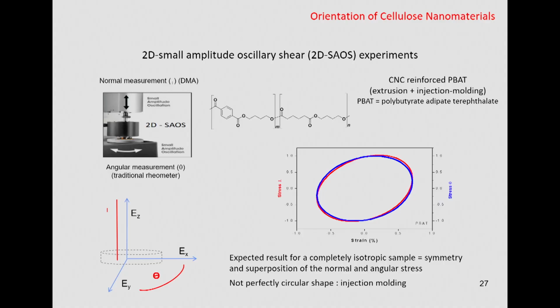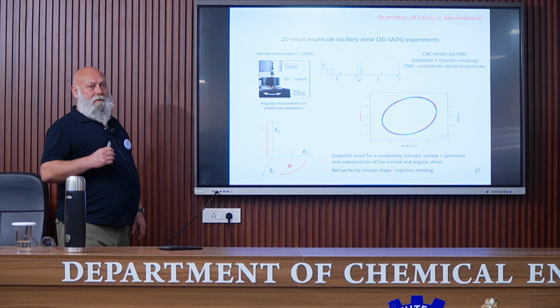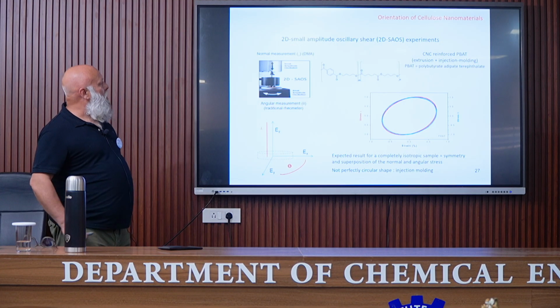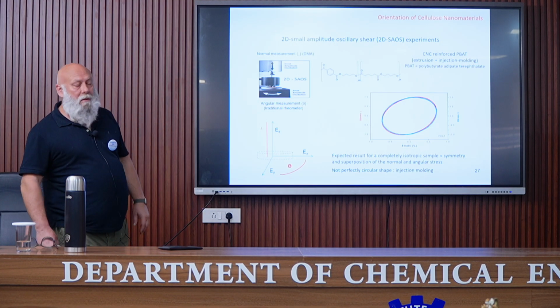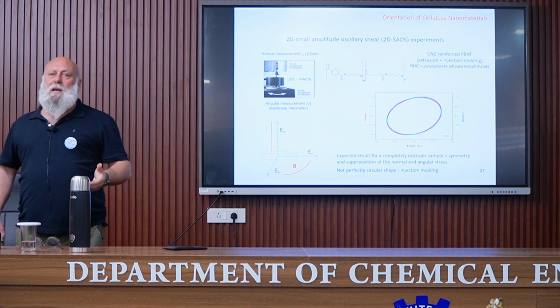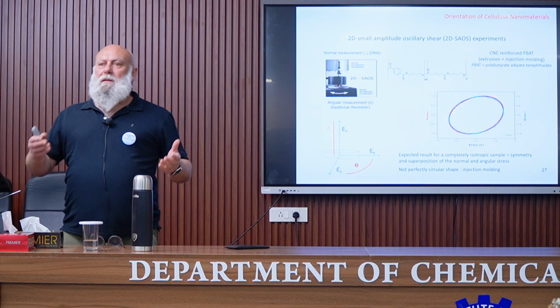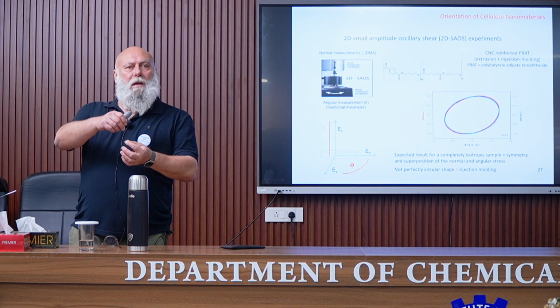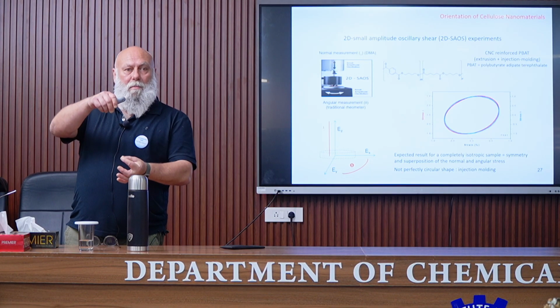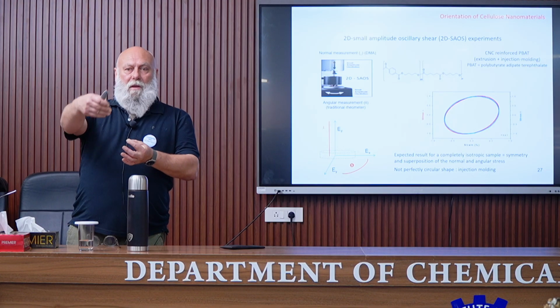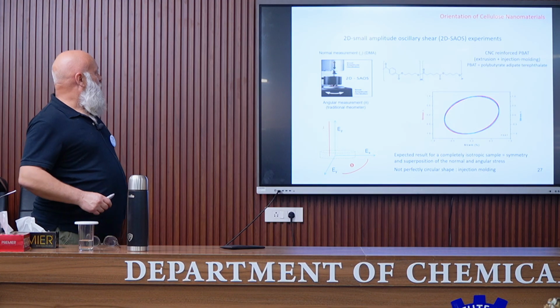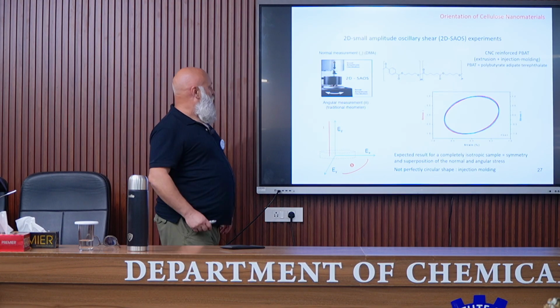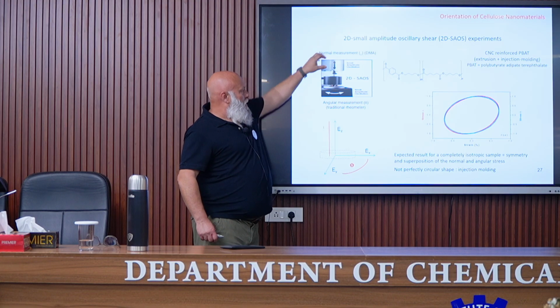This time it was a Brazilian PhD student, we also tried to evidence this orientation using a very specific technique, which is the 2D small amplitude oscillatory shear experiment. In fact, it is like dynamic mechanical analysis, except that in dynamic mechanical analysis, you know that a periodical or sinusoidal stress is applied to the material, for example in tension, and the deformation is measured. In this case, the deformation was applied in 2 directions, perpendicular direction and also in rotation.